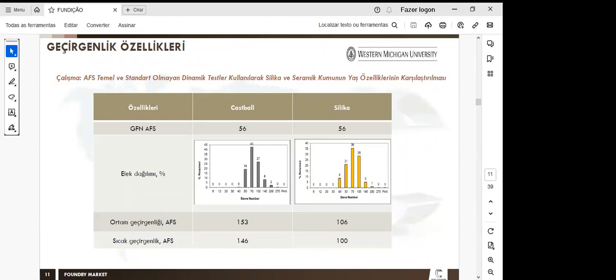Here we have some results from a university in the United States. Just to confirm, we have a comparison of two foundry sands, Castball and silica. The particle size distribution curve is the same for both, as you can see. And Castball presented higher permeability when compared with the silica. Just to confirm about the shape of the grains, the rounded shape gives us high permeability.